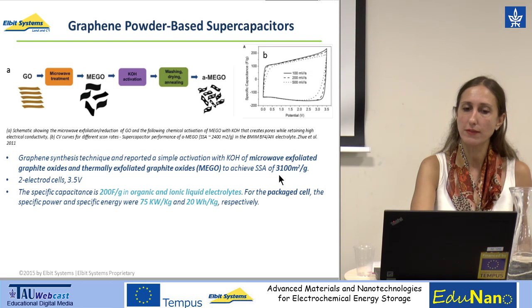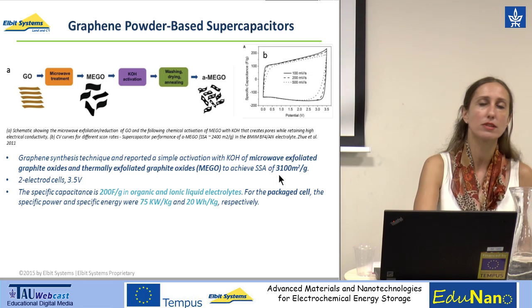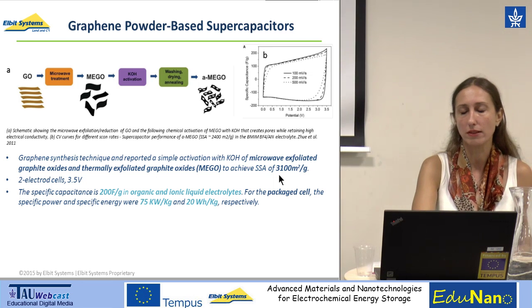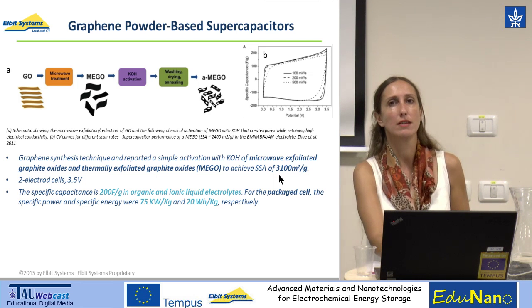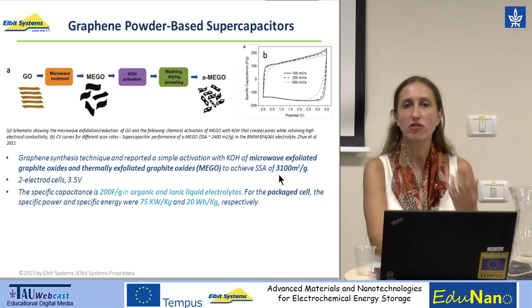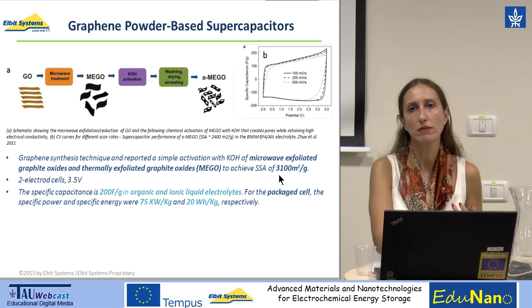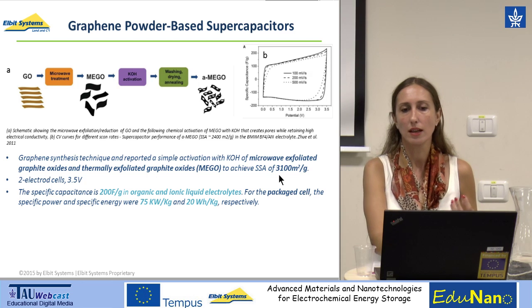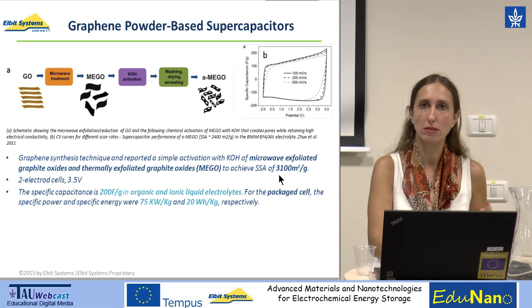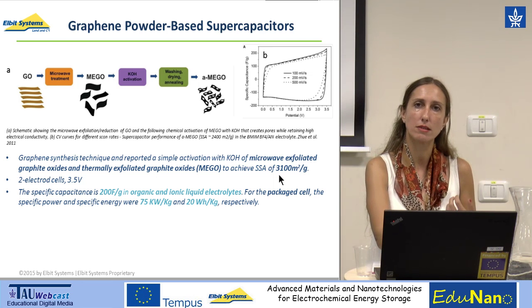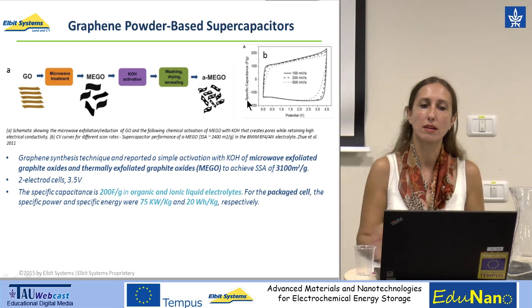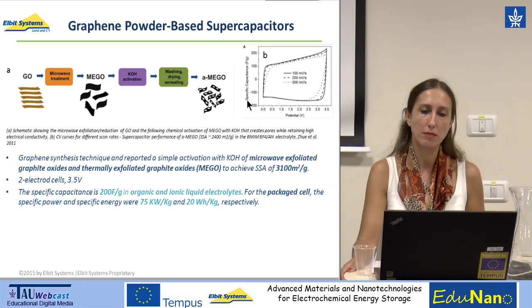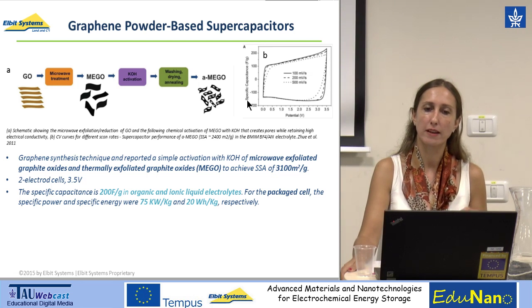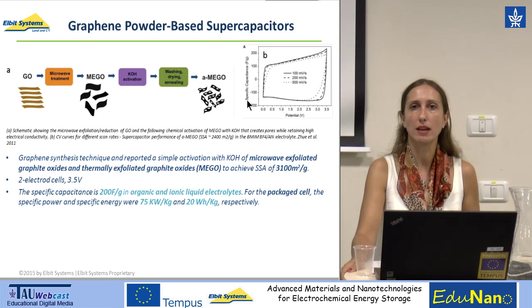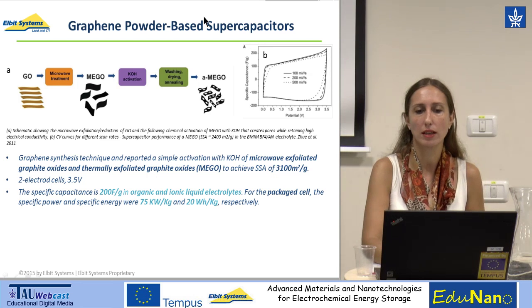not only that, but the specific capacitance attained in this kind of cells was 200 farad per gram, which is a huge capacitance when you take into consideration that you use, first of all, an ionic liquid mixture of organic solvent, and this high capacitance value does not result only from the high surface area values that were attained via the KOH activation process, but it was attained mainly due to the macro size, or let's say pore distribution attained in the graphene oxide flakes or layers.